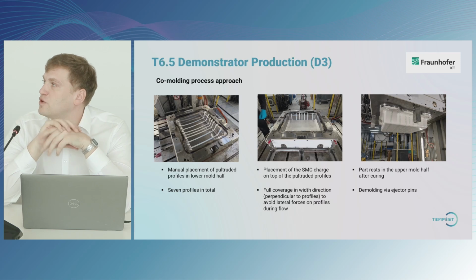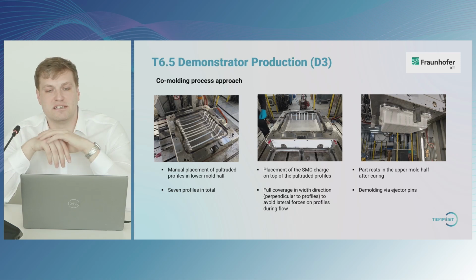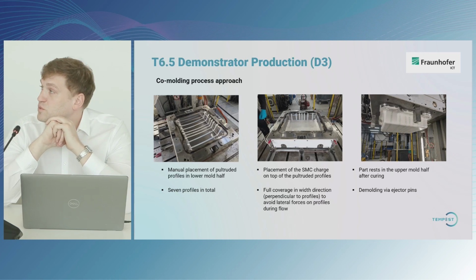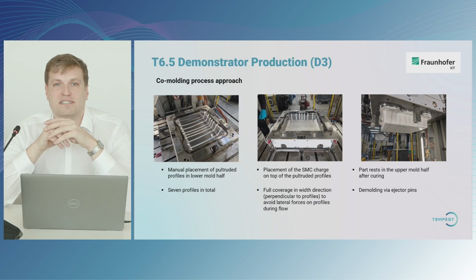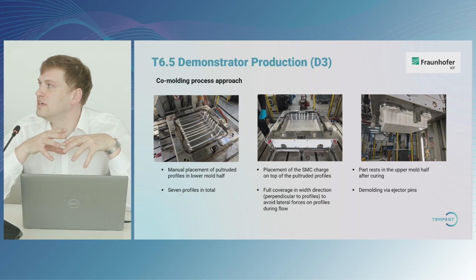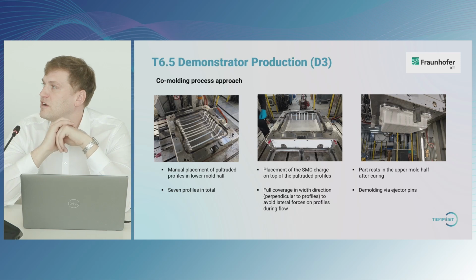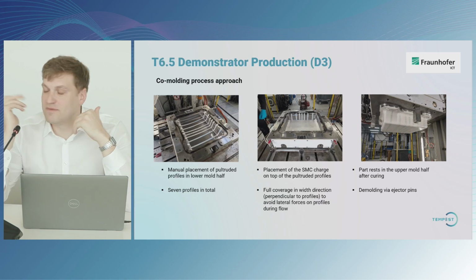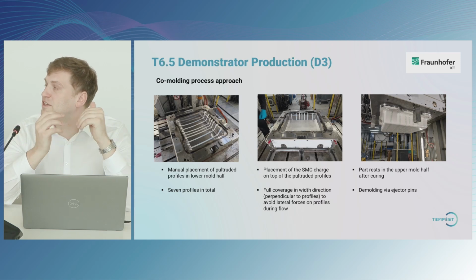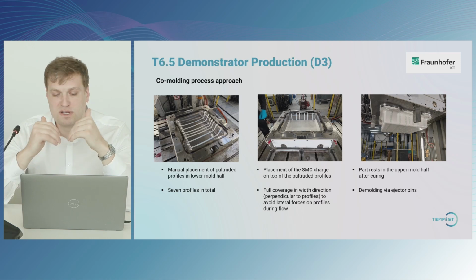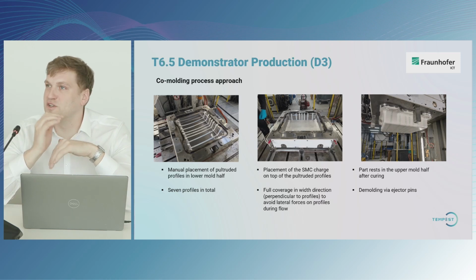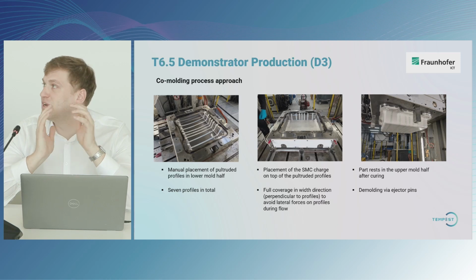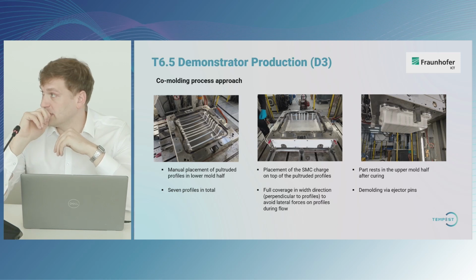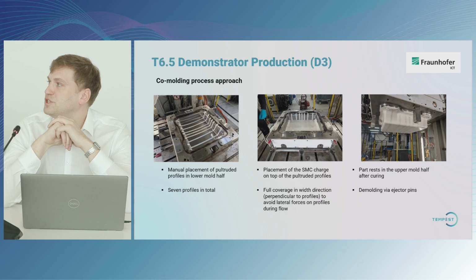So here you can see all the profiles set into the mold. In total we used 7 profiles, and after they are placed, we then place the sheet molding compound. And what we noticed is that it's really important how it is placed, or what the size of the SMC cover is, because after placing, everything is pressed together, and then you need to consider the material flow and make sure that the flow does not cause any fiber washing or displacement of the profiles. Therefore, you can see the final result of the mats that we used.